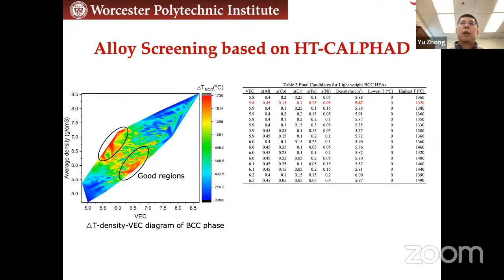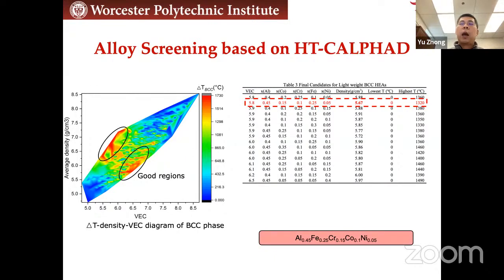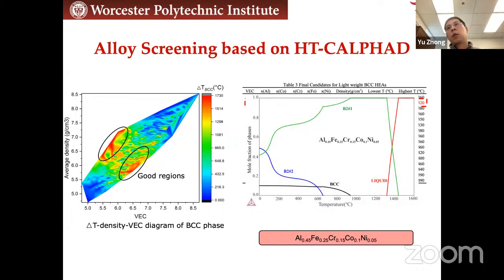This satisfies our needs, and after we got this composition, we did this one shot, these state calculations for this alloy, and it does show that this is a very good alloy. It will come with BCC and B2 phase, and has a very high melting temperature. So I hope I convinced you that these high throughput calculations can be very useful to quickly find the composition range you are looking for.